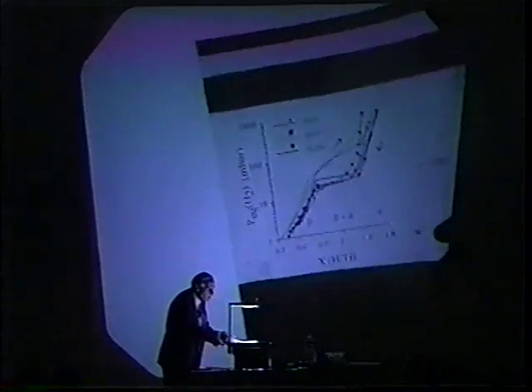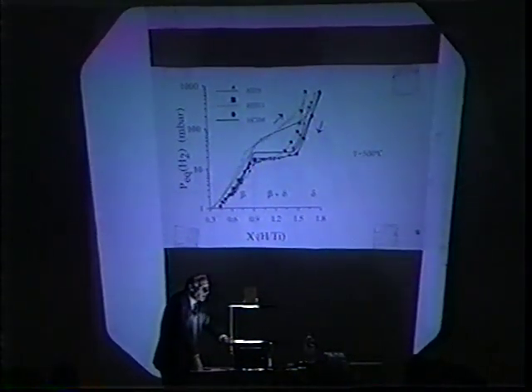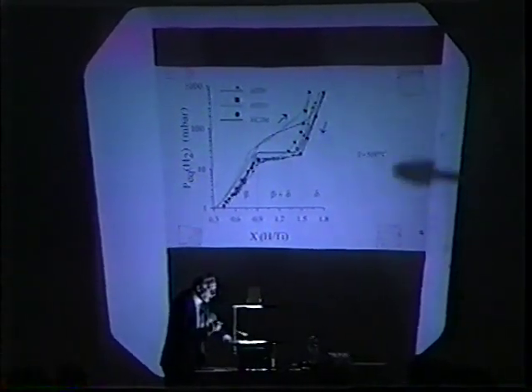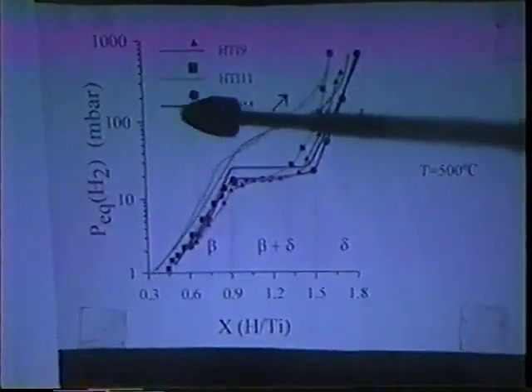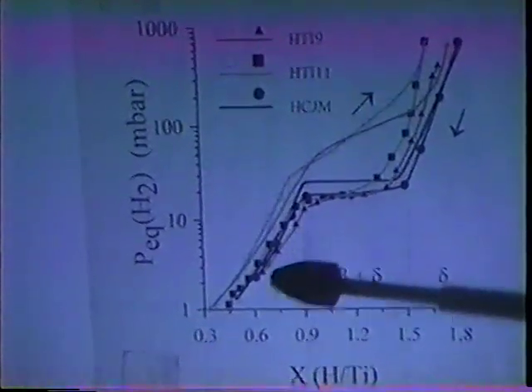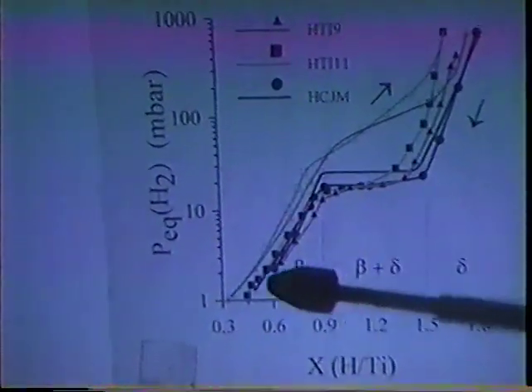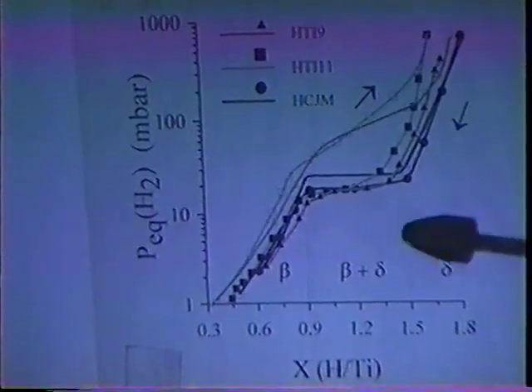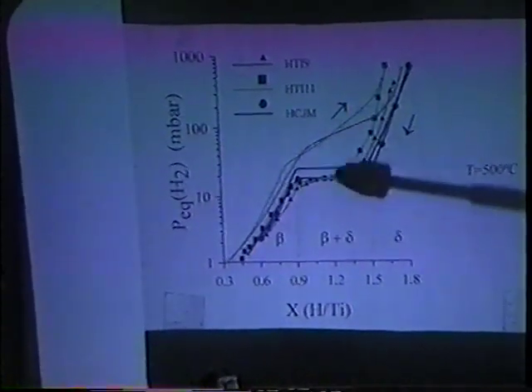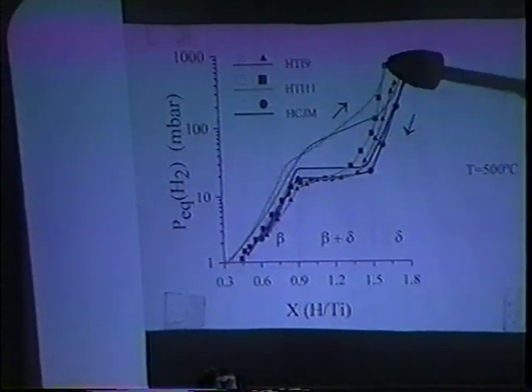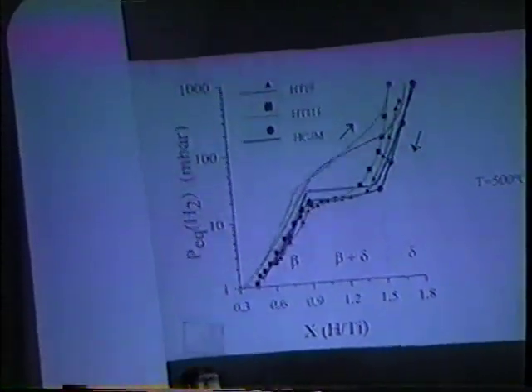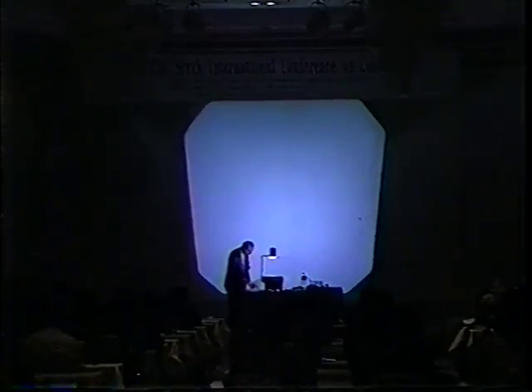The tungsten has a negative influence on the hydrogen transmission characteristics of the titanium. This is a proof of that. You can see here two samples grown by us and one commercial sample. The commercial sample has no tungsten, so you can see that the PCT curve shows no hysteresis and a high loading. However, our samples with contamination of tungsten have a high hysteresis and a more difficult loading at high pressures. So, as I said, the samples we finally use for cold fusion experiments were produced with low tungsten temperature, so no tungsten contamination.